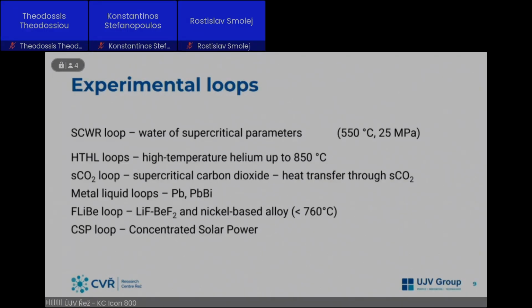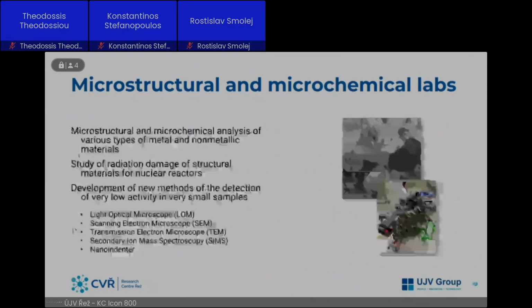There is a laboratory for liquid metal loops like lead, lithium, and lead-bismuth, which are for fast reactors or for fusion applications. As for the fluoride salt loop, it means there was testing of the corrosion capabilities of lithium fluoride, beryllium fluoride, and other salts, for molten salt reactors or high temperature reactors cooled by fluoride salts. And there was a specific one, a concentrated solar power loop, for testing how to get heat from the sun and how to use it as a power source.